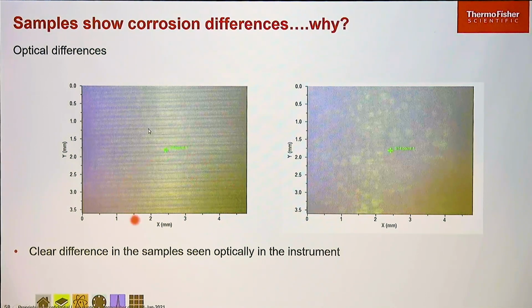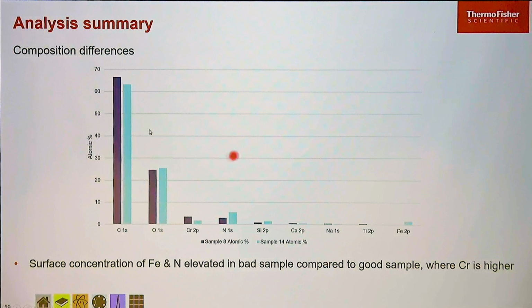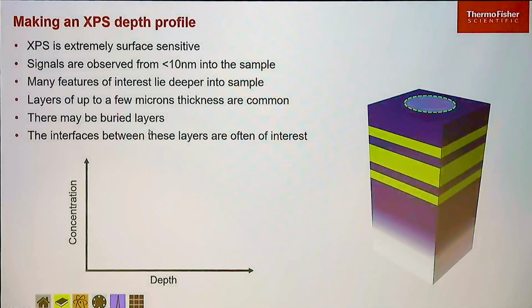So we can obviously see optically there's a bit of a difference here, but that could just be milling or surface finishing or whatever. It's not necessarily anything to do with the chemistry. And if we just have a look at the composition, largely they look fairly similar. Sample 8's the good one, sample 14's the bad one. We can see there's a similar amount of carbon, similar amount of oxygen, maybe a little difference in chromium and nitrogen there, but nothing too much. And so what we probably need to do, again, these parts have probably been handled without gloves or just where we're going to analyze, and so we need to clean them off. So we'll do a depth profile.